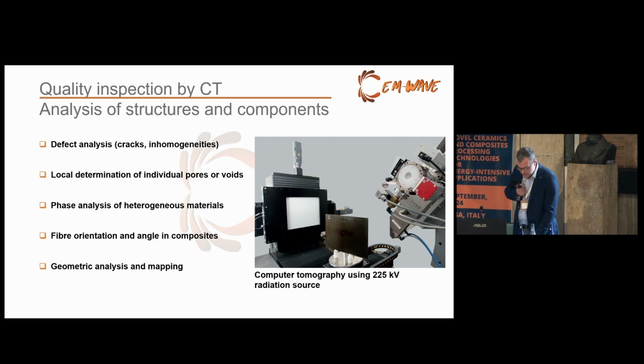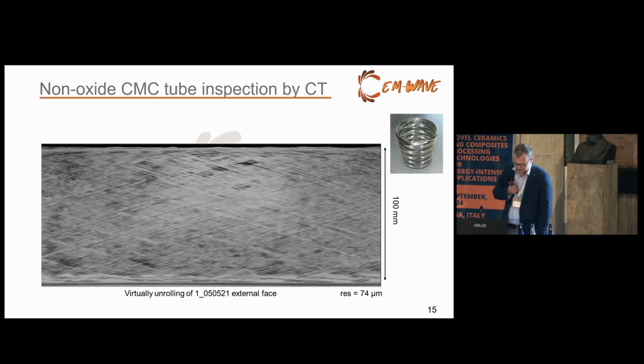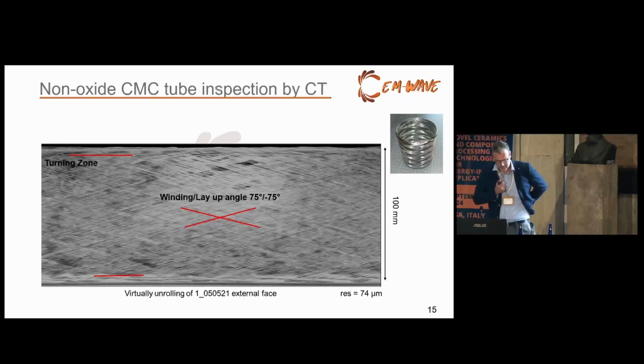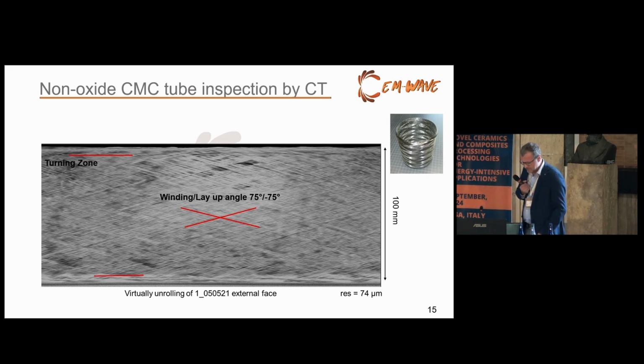What we should keep in mind is that computed tomography is a technique which depends on the sample size. So when you have a 100 millimeter tube, the resolution will be at best 50 to 60 microns, and any effect which is smaller, you may not see. So you should keep this in mind. But anyhow, you can unroll these 3D volume CT images and check whether your 75 degree angle layup is still the way you want it. You can also see the turning zones there, which we always wanted to cut off.